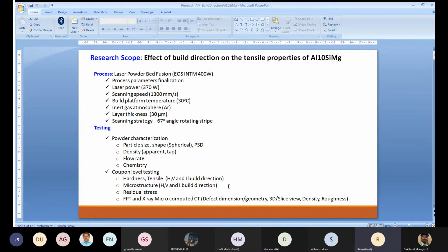And what are the tests we have conducted? There are 2 phases of testing. One is before printing the samples, that is on the powder, to ensure that the powder has good quality in terms of size, shape, particle size distribution, apparent density, tap density, flow rate, and chemistry.